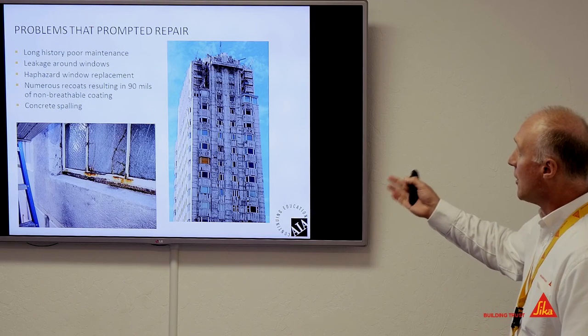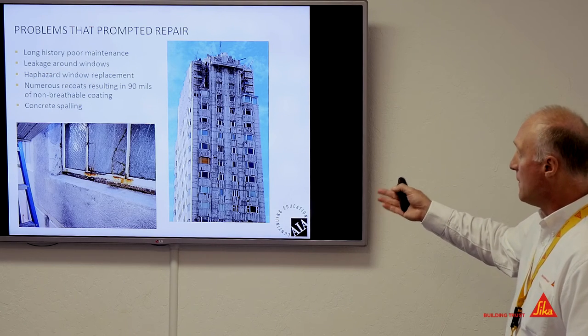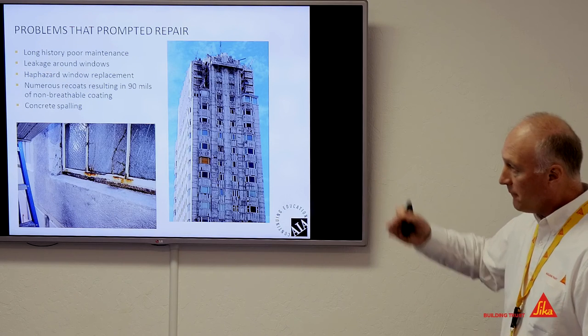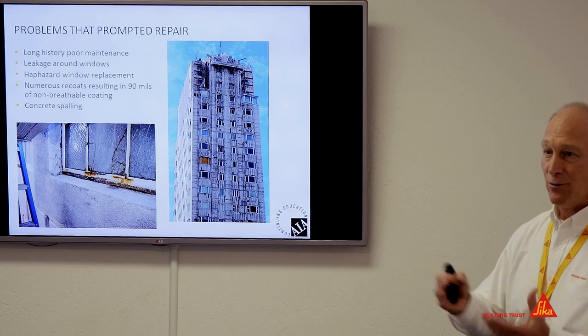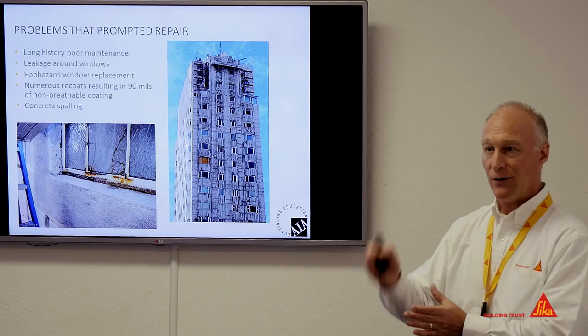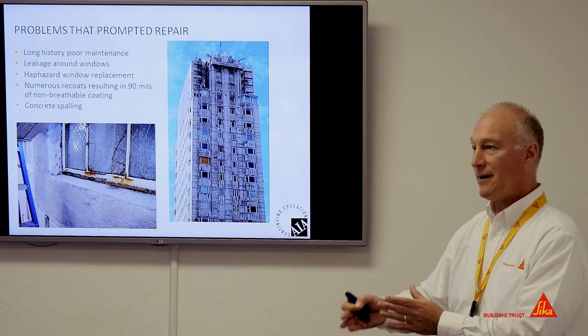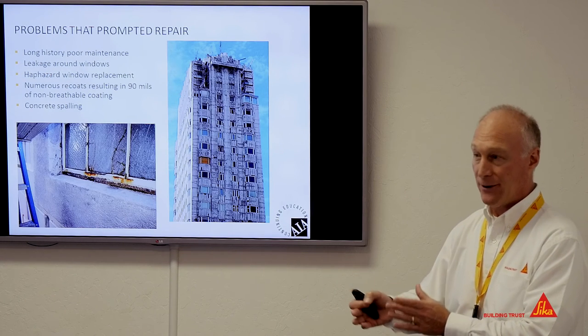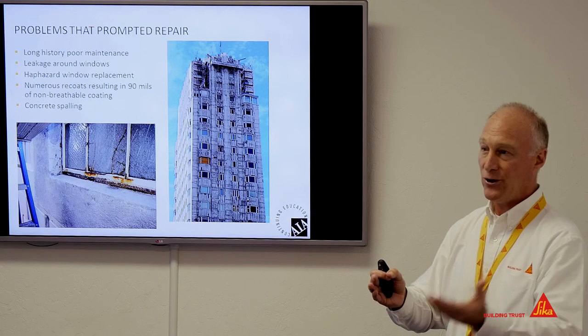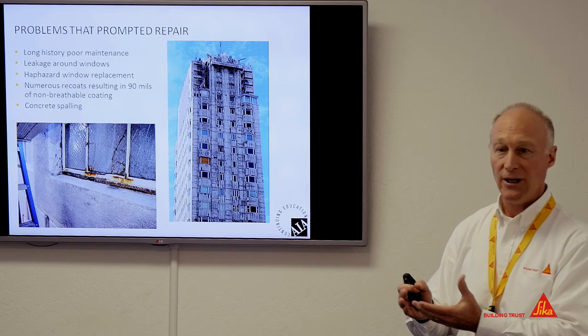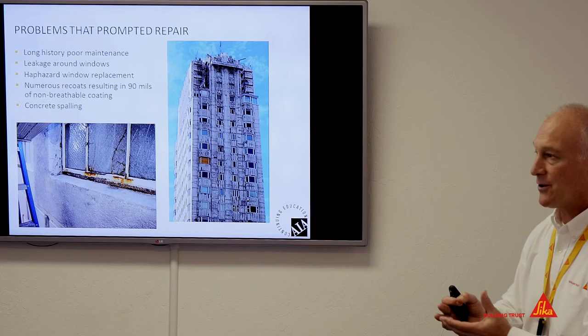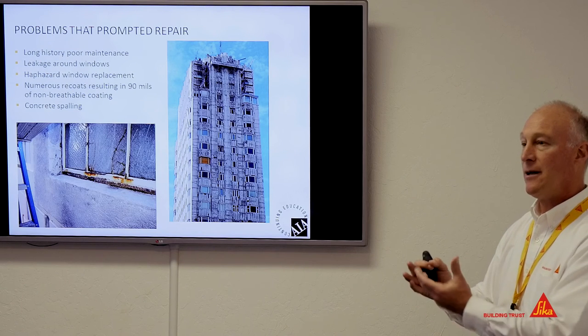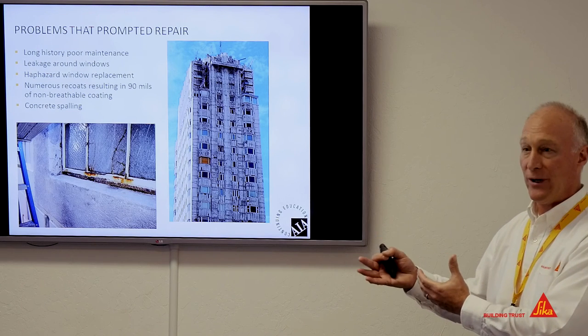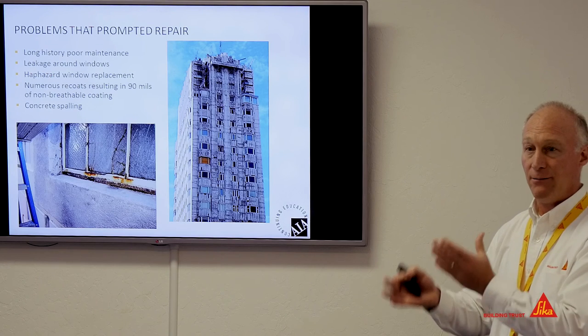There were a lot of coats of coating on the building. The balance now is, even if you're using a breathable coating, if you keep applying coat after coat, at some point that coating may become unbreathable, which means you could lock moisture in, which is really not a good thing in terms of the steel environment, but also could cause premature failure of the coating. So there is that balance.